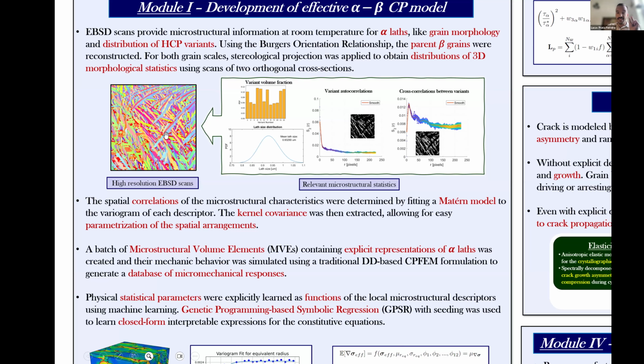Now, these alpha laths are very, very fine and very small. So if we were to model a large volume of it, it would be pretty much computationally unfeasible, because imagine just discretizing this. So we want to embed in an effective crystal plasticity model these parameters that describe the microstructure, such that we don't have to explicitly represent the grains.